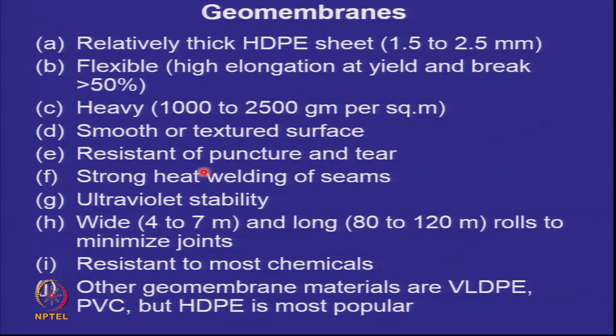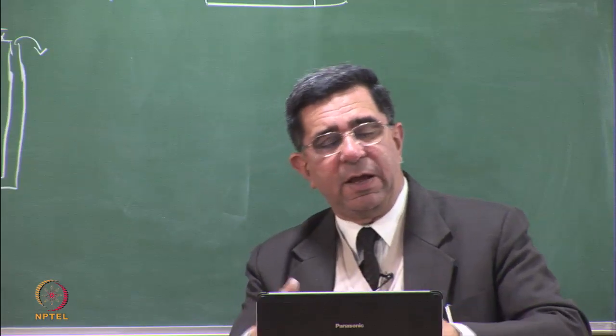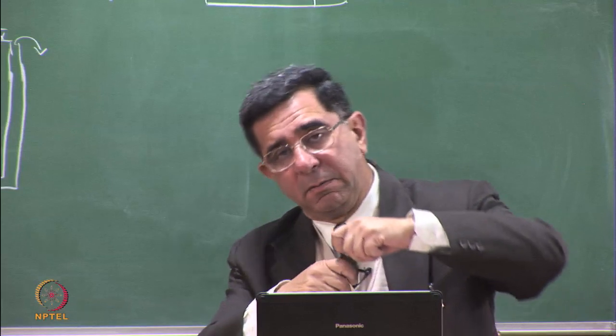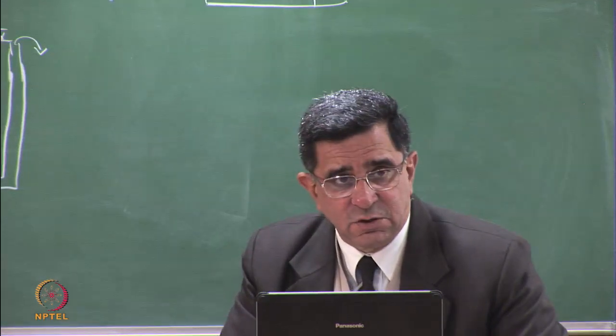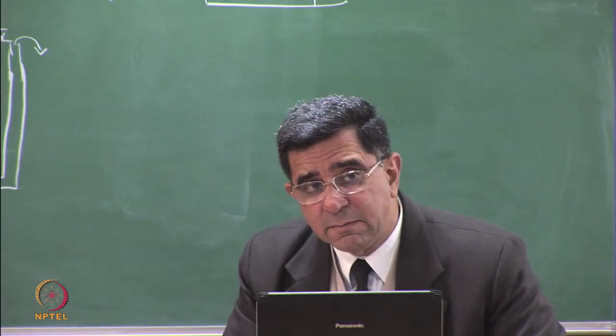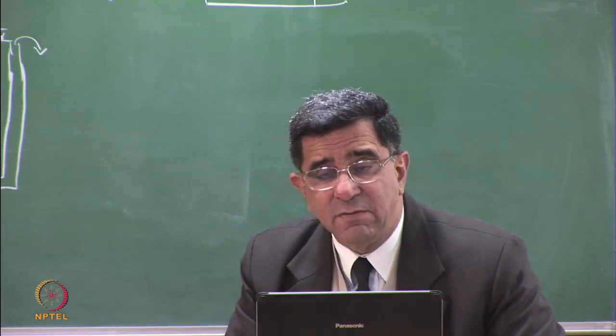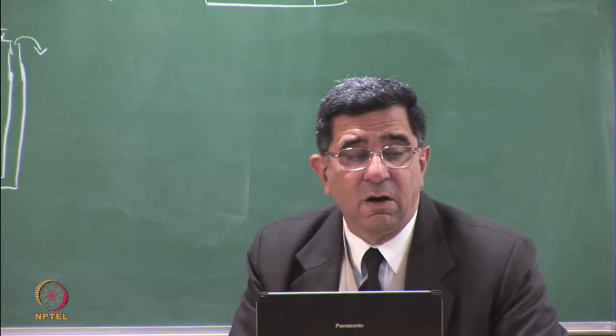So, just to recall, geomembranes are relatively thick polymer sheets. Typically in a landfill, you'll find them to be 1.5 to 2.5 mm thick. For very high landfills, they'll be 2.5 mm thick. They are flexible. When I say flexible, how much will they elongate before they break? So if you do a tensile strength test on an HDPE geomembrane, before it yields or breaks, it will have 50% elongation.